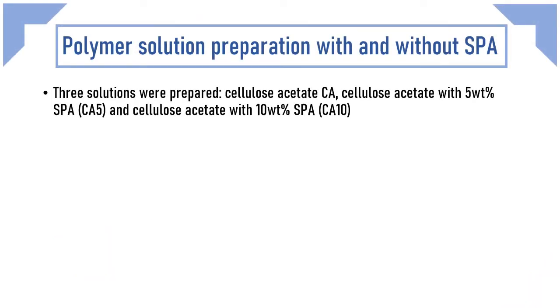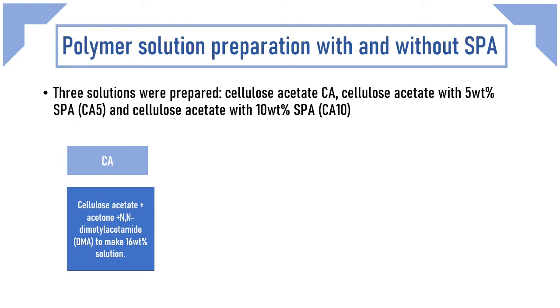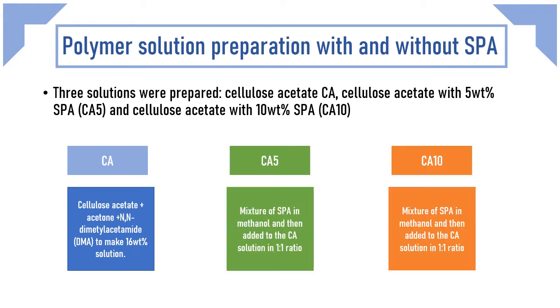Polymer solution preparation with and without SPA. For the experimental part, the authors prepared 3 different solutions of cellulose acetate, 2 of them with SPA. For the first solution, cellulose acetate was dissolved in a mixture of acetone and DMA to make a 16 weight% solution for electrospinning. In 2 other formulations, 5 and 10 weight% solutions of sodium polyacrylate were prepared by mixing SPA in methanol and then added to the prepared cellulose acetate solution in 1:1 ratio.